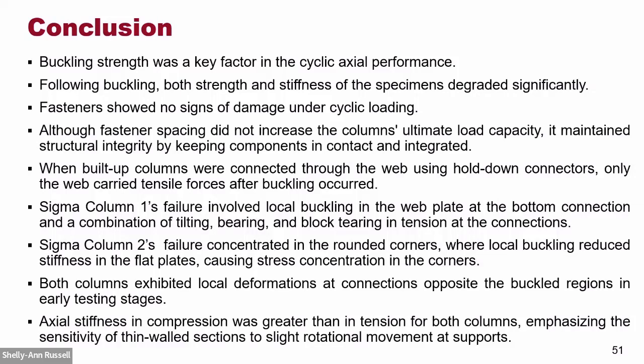As a conclusion, buckling strength was a key factor for the axial behavior of these specimens. Following buckling, both strength and stiffness degraded significantly. Fasteners showed no sign of damage under cyclic loading. Although fastener spacing did not increase the column strength, it kept the integrity of the specimens together, and they were always in contact during the cyclic axial loading in compression.